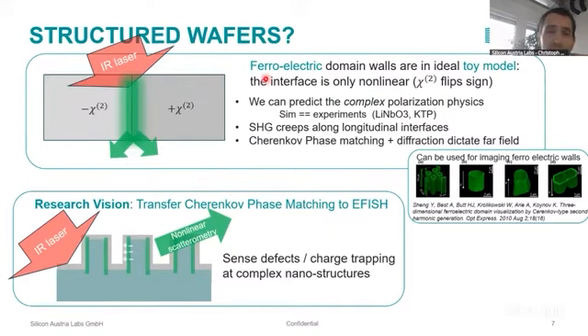Ferroelectric domain wall is special because it only has a nonlinear interface, and there's no linear interface. This means the refractive index is the same, but the second order susceptibility is different because the crystal rotates 180 degrees. And then there's a phenomenon called Cherenkov phase matching, where basically the signal creeps along the interface and has phase matching condition, and therefore it gets very strong. And then in the end, you get 2 outgoing beams that you can detect. And we solve basically a theoretical problem about the polarization physics that happens at this interface. So this was disputed, and we can now fully simulate what happens in the experimental data.